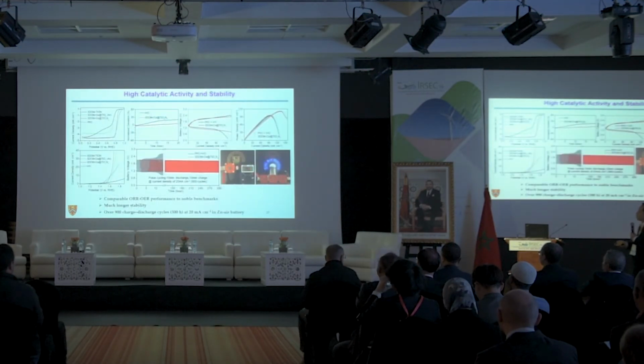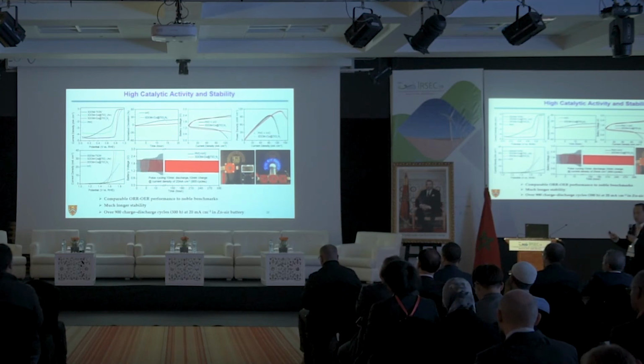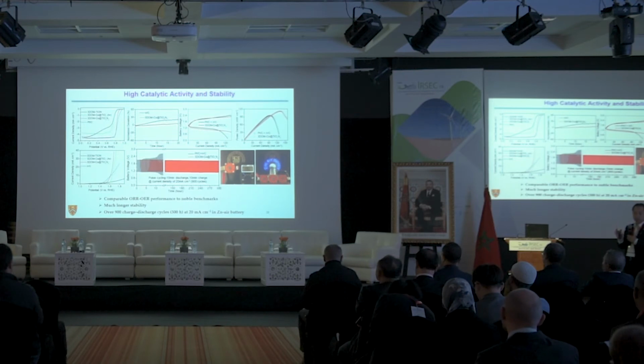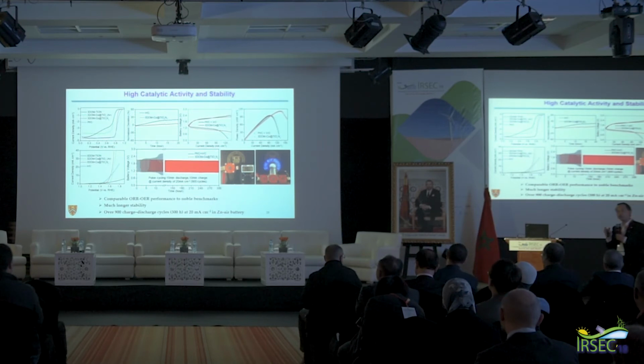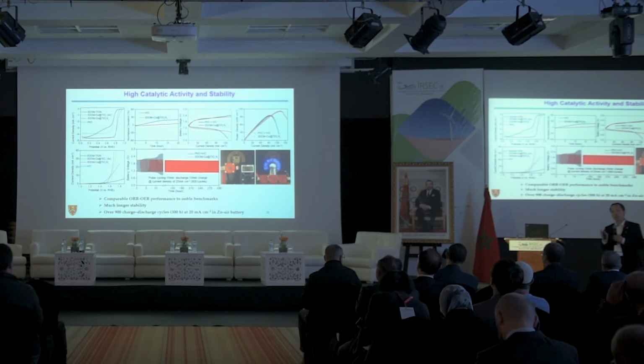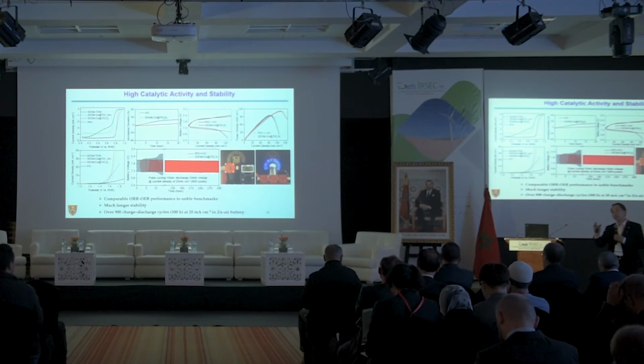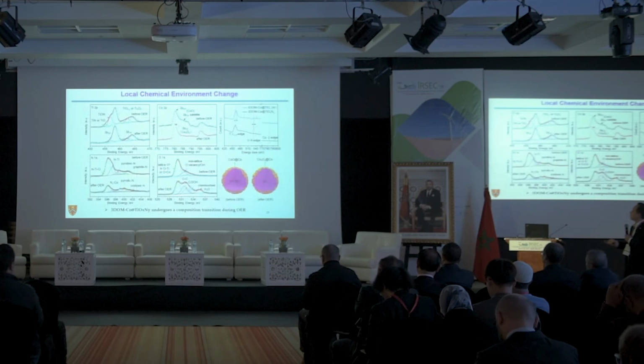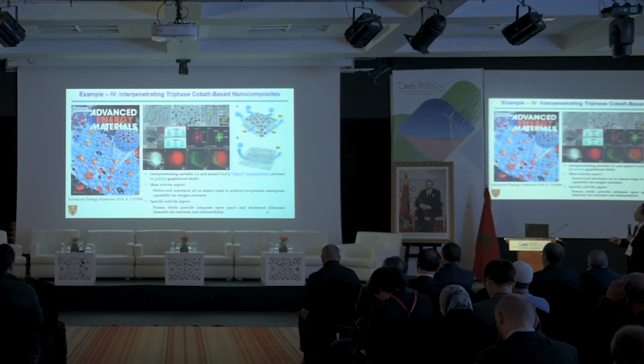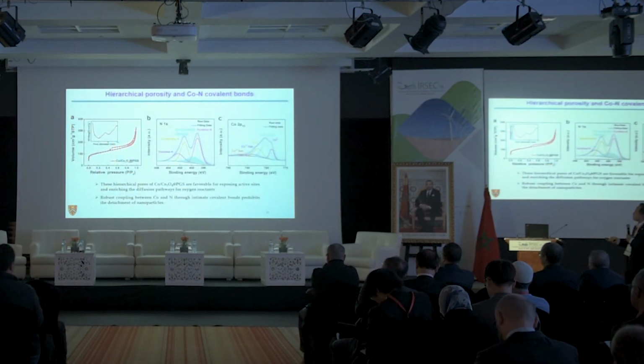With this catalyst, we also proved it is very stable, because for this catalyst you don't even need to use carbon inside. We can use titanium nitride together with some other metal like cobalt. As you know, titanium nitride is very conductive itself and more durable than carbon during charge and discharge. So that's a new type of catalyst we designed, and we will not involve any carbon inside. This we will bypass quickly.